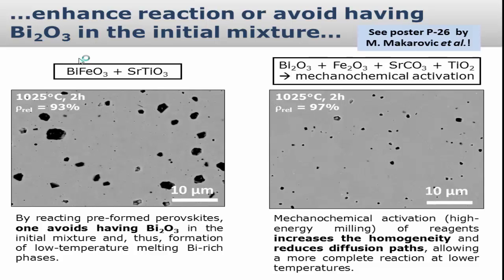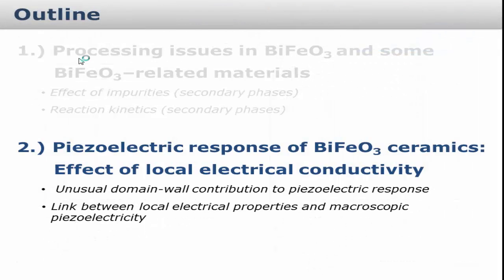So what you can do, for example, is to prepare perovskites before and then mix together. And as you can see, it works very similarly to the mechanical activation. There's some difference here in densities, but this is meant to show the principle of how you can avoid this bismuth-rich, low melting temperature liquid phases. Okay, that's for the first part.